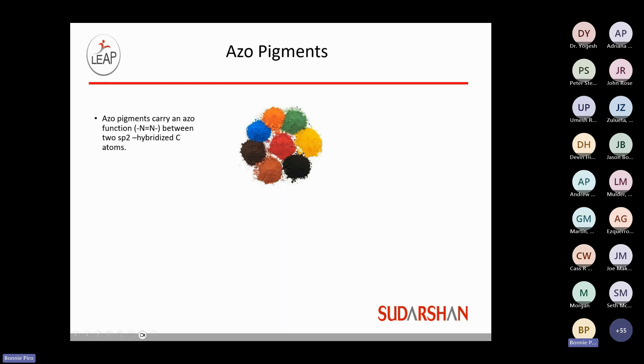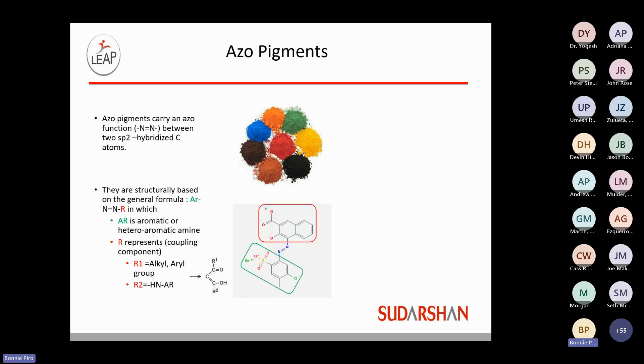Azo pigments are designated with the azo nitrogen double bond that distinguishes all azo chemistries. In some cases, you might see two of those pairs of double-bond nitrogens with a disazo pigment. They are structurally based on a general formulation where AR is typically some sort of aromatic amine that creates the base. In the middle, you'll see the nitrogen double bond, and then R represents the coupling component that comes along to create the specific chemistry or color index you're trying to achieve.